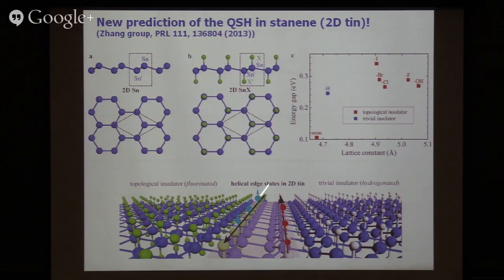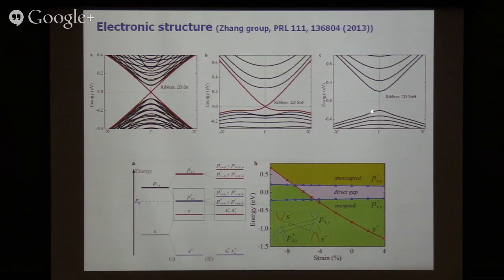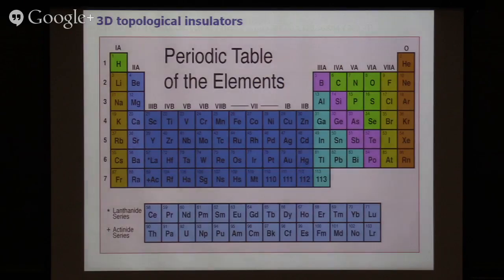Then we predict that this system will form a buckled honeycomb lattice, where the atoms on both sides are a little bit buckled in the z direction, but still more or less a honeycomb lattice. And we predict that in this system, it will be a two-dimensional topological insulator with a topological gap of 300 millielectron volts, 10 times higher than room temperature. It's also very interesting, a natural continuation of graphene research. So we're proposing this material, and a lot of groups around the world are trying to get it.